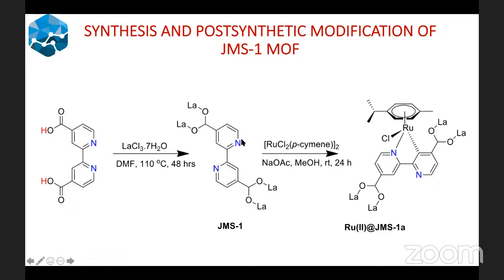And as you can see here in the MOF, the conformation of the nitrogen sites changes. This means that if you want to carry out methylation, it will be very difficult, as this ligand has already been locked in the MOF with this kind of conformation. But of course, you can carry out what we call a cyclometalation, where you want to activate that CH bond, so that your ruthenium can coordinate to the carbon and coordinate to the nitrogen sites, as given here.